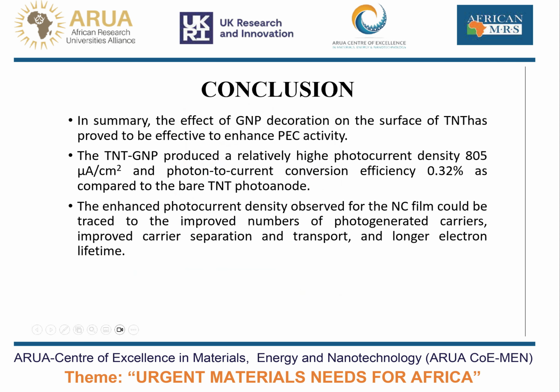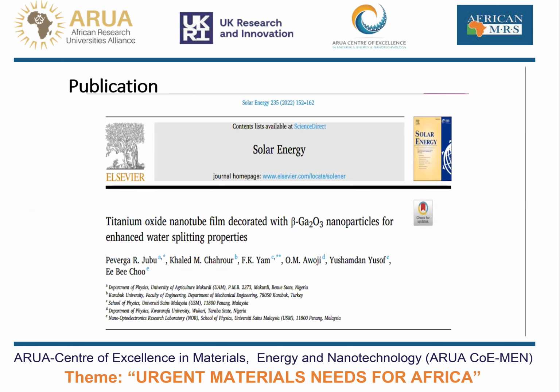And in conclusion, the effect of gallium oxide nanoparticle decoration on the surface of titanium oxide nanotubes has proved to be effective to enhance the photoelectrochemical activity of the material. The titanium oxide nanotubes decorated with gallium oxide nanoparticles produce a relatively higher photocurrent density of about 805 microamperes per centimeter square, and a photon to current conversion efficiency of 0.32% as compared to the bare titanium oxide nanotubes. So the enhanced photocurrent density observed for the nanocomposite could be traced to the improved number of photogenerated carriers, improved carrier separation and transport, and longer electron lifetime. This work, we have been able to publish it in Solar Energy.